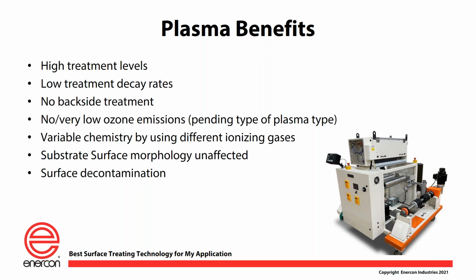Because we're ionizing a gas that we're bringing into the treater, we don't typically experience any reverse side treatment, or treatment behind the web, backside treatment, because there's no gas back there. So there's no process gas behind the web. We can't ionize it, and if we can't ionize it, then we don't get any negative from that. The ozone emissions that are generated from an atmospheric plasma treater are typically less than that of a corona treater, and there's a number of reasons for that.